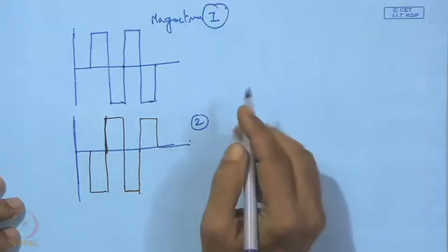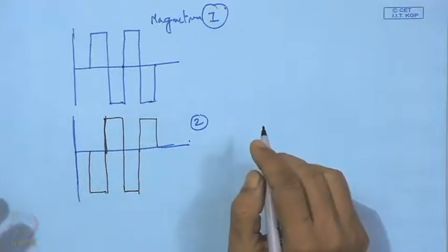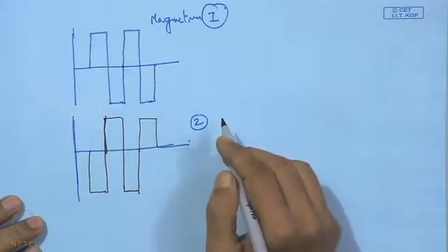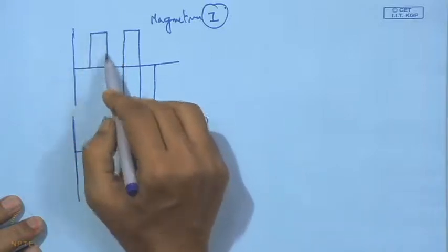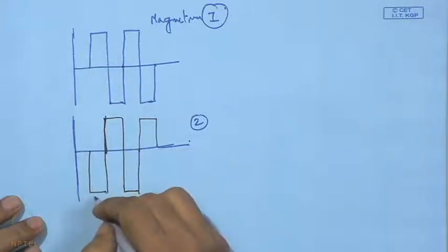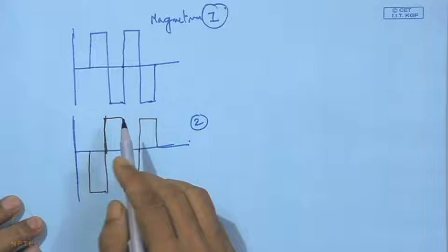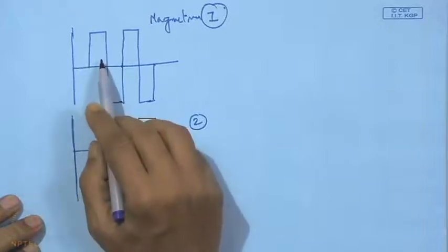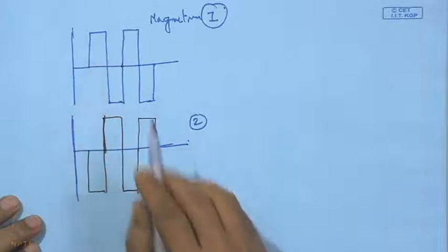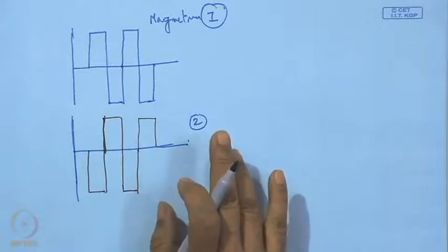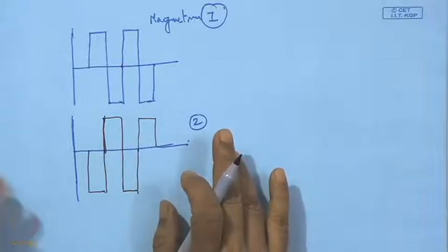So, what we see is that we must have a pulse generator, and this pulse generator has to be coupled, but in this case just one pulse generator can be coupled with two targets, like a twin target. When one is under positive polarization, the other one will be with negative polarization, and this way one power supply can be well utilized. So, one is active and the other at that point is not active, but their accumulated charges are neutralized and two are functional, and they can be made functional just by use of one pulse generator.